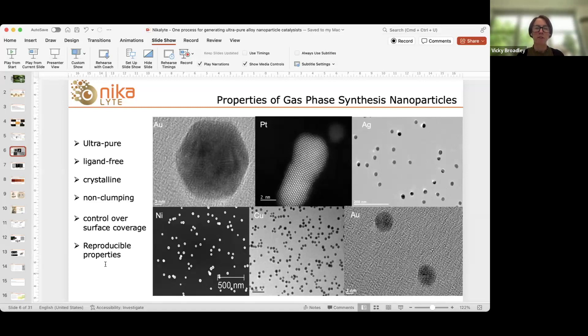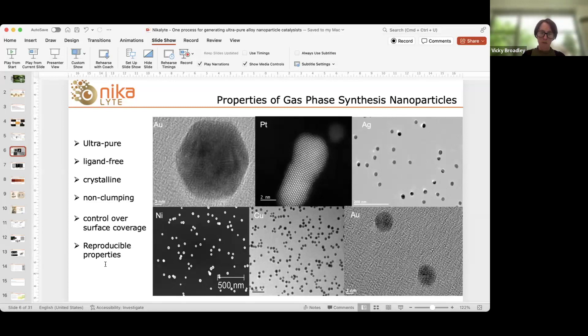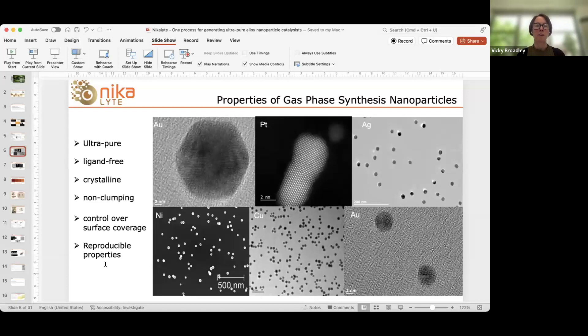Another important characteristic is that these nanoparticles are non-clumping — they don't stick together. They land on the surface and stay where they land, giving a beautiful dispersed coating. As you increase deposition time, the coating builds up but they still won't form agglomerates. You get a really nice, even coverage of non-agglomerated nanoparticles. The process is also repeatable: you can return to the same conditions of pressure, gas flow, and power, and produce the same materials again — which is critically important when optimizing a process.